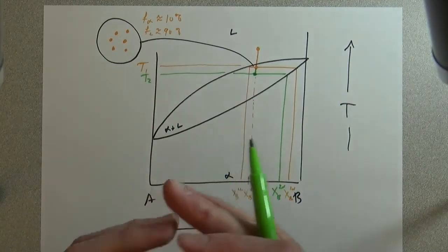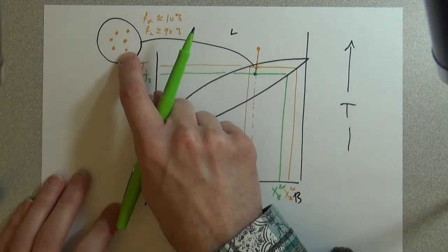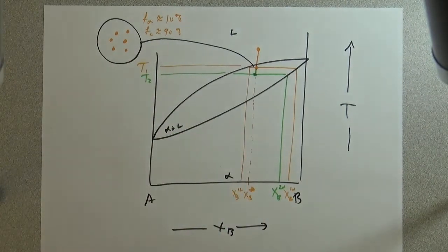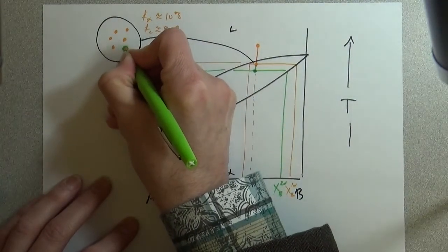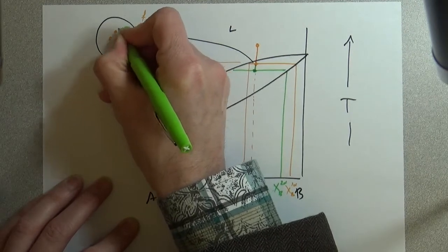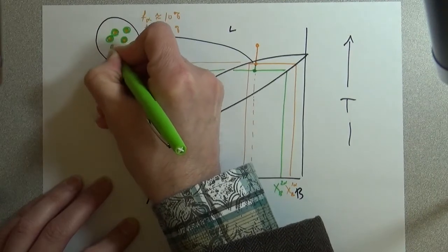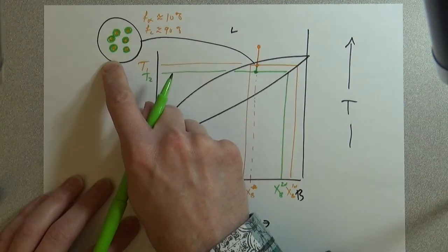So when we precipitate this new solid, that forms on the outside of the existing solid. And because diffusion in a solid is relatively slow, especially compared to in a liquid, we know that what's going to be coming out is actually going to form on the outside of those existing grains.